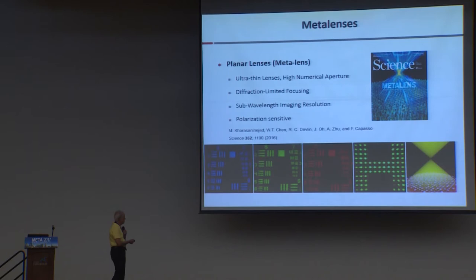You know the ALD process cycle, how much it takes. It's 0.75 angstrom of titanium oxide, and each cycle takes 17 seconds. So you can put the numbers, and you see that these reactors can in the future crunch through up to 70,000 chips per hour to make your lenses. So this is not a limiting factor. Now, this was our first step to make a high quality lens. In fact, I was on sabbatical at Zeiss, and they told me, well, Federico, you want to try it out. Make a high numerical aperture lens, infinity corrected, and then compare it to an objective. So that's what we did. And so these, we use Berry phase, so they are polarization sensitive.